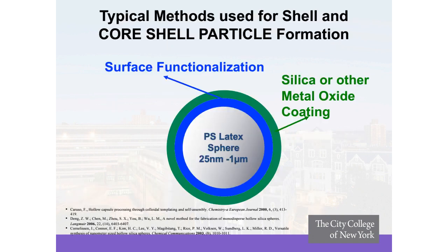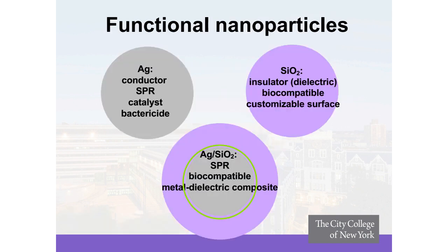As part of designing functional materials through these templated approaches, we've also developed techniques in our laboratory where we can not only form hollow shells, but we can also form core shell particles where there is a core functionality, typically a metal in our cases, that is coated with a particular shell. And then these particles can be assembled onto substrates using approaches where we tailor those 4 interactions mentioned.